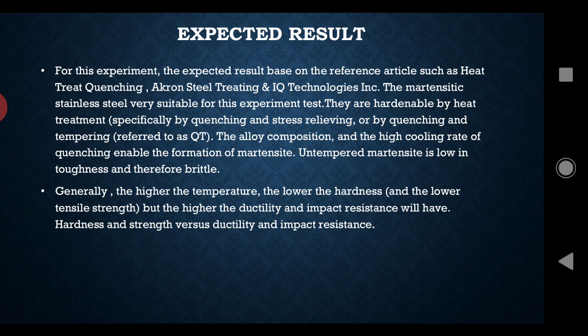Okay, for the result, we don't have a preliminary result because we could not use the laboratory at FTK because of the pandemic. So based on the reference articles, heat treat quenching, Akron Steel Treating, and IQ technologies, martensitic stainless steel is very suitable for this experiment because it is hardenable by heat treatment, and the alloy composition and the high cooling rate of quenching enable the formation of martensite,